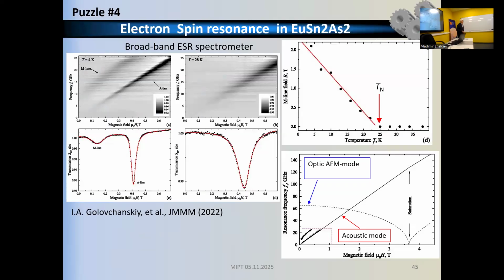Let me move to the last puzzle of my story, which is electron spin resonance. Again, these measurements were started at MIPT by Igor Golovchansky and Vasily Stolarov, and they studied the same crystals, which are supposed to be topologically trivial semimetals with simple van der Waals interlayer bonding, and the simplest antiferromagnetic easy-planar anisotropy. Instead of what is anticipated, they saw the splitting of the electron spin resonance. It's supposed to be a single line, but instead Igor observed two lines, which develop.